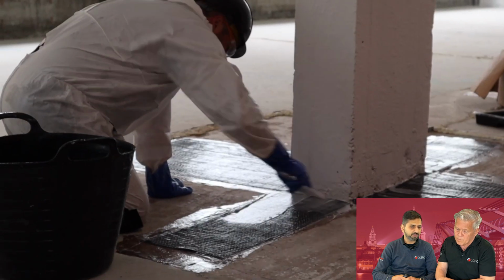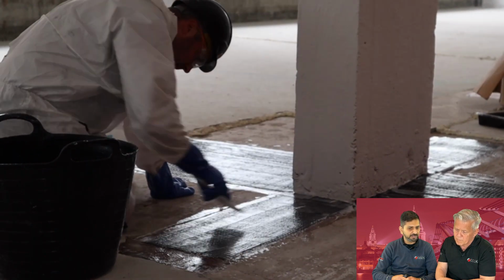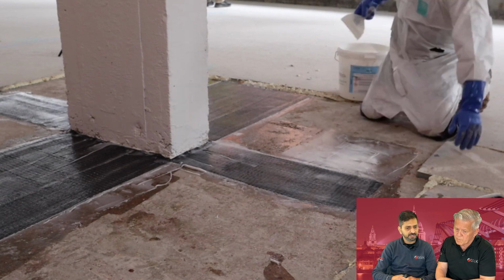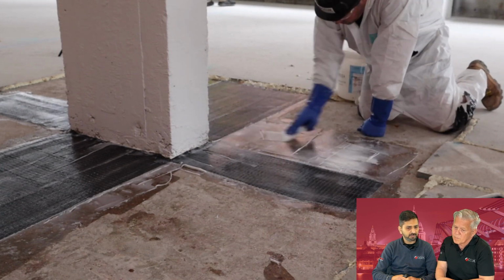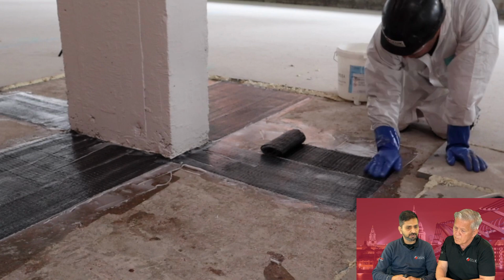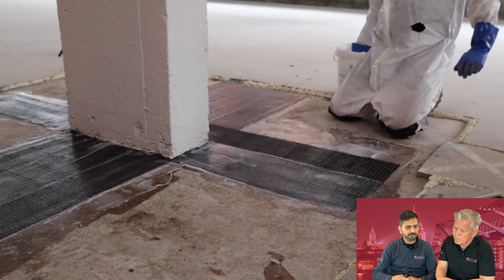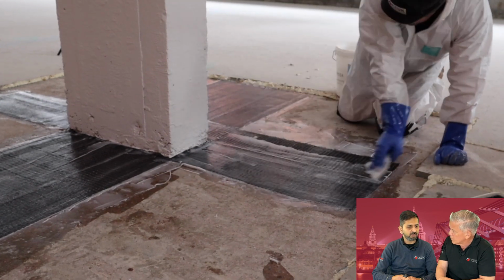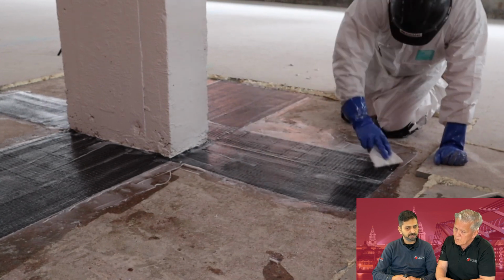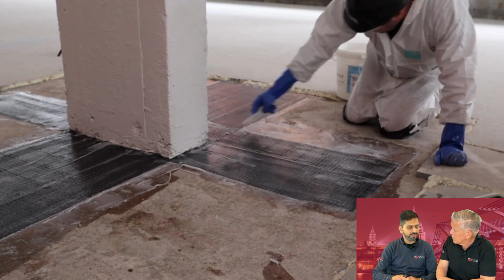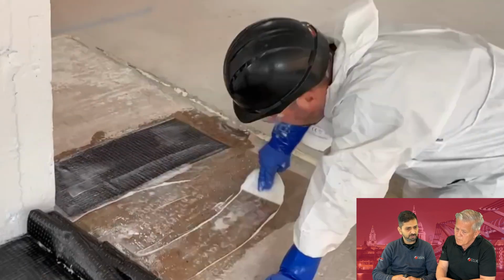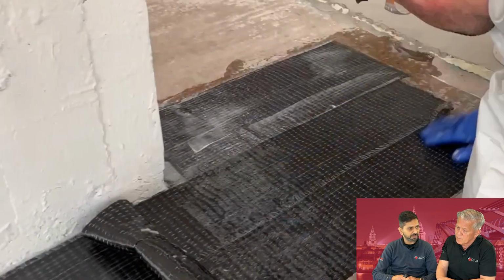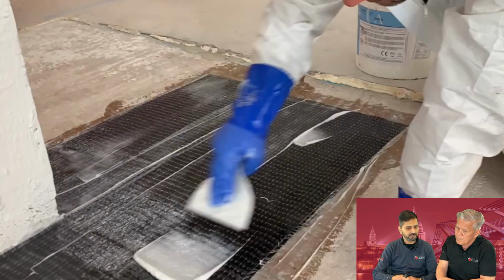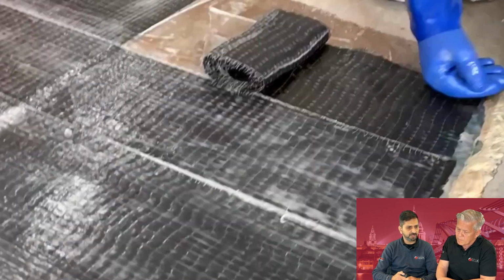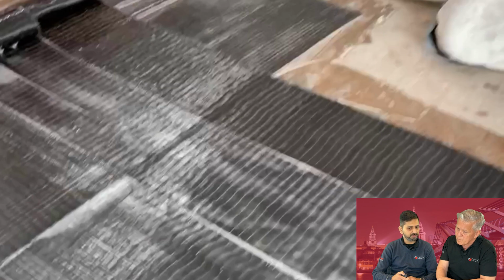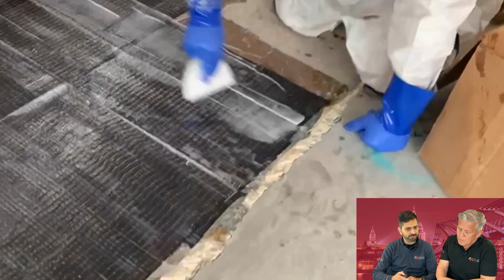Now there are still people out there who do dry layup. In dry layup, they just prime the area with the pure epoxy and try to patch dry fiber onto that primed area using their hands, and then put another coat of epoxy on that dry fiber. By doing that, they cannot guarantee 100% resin impregnation through every fiber, and that dryness will lead to a debonding or delamination failure. So to avoid that, the application has to be a wet layup method, especially in a fabric system. That's one of the key points people should make note of: on any of their projects, if a contractor is doing FRP application, it needs to be the wet layup method.